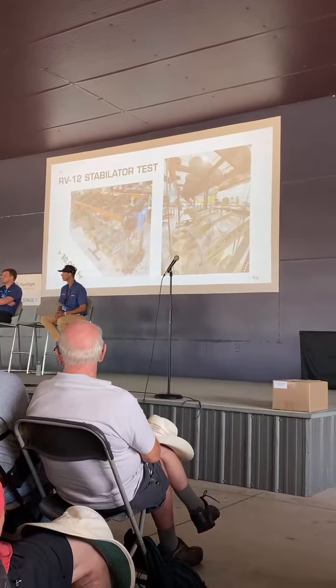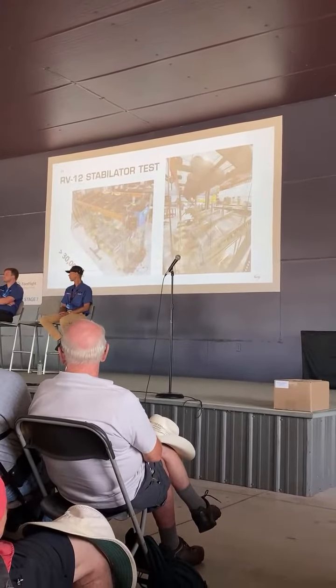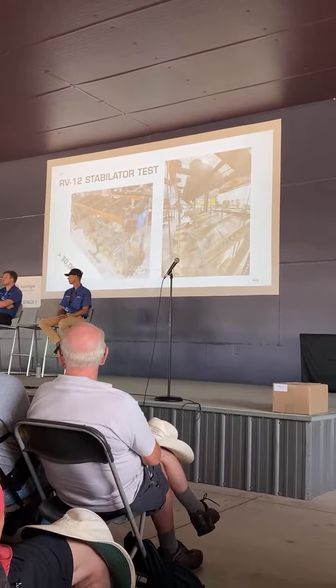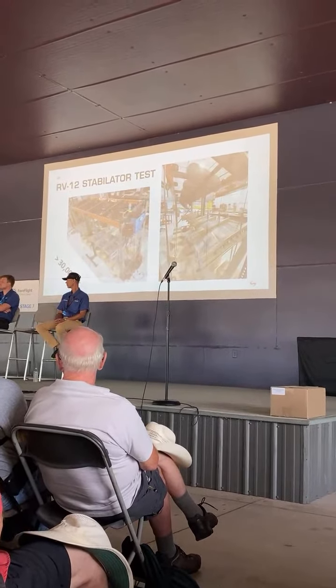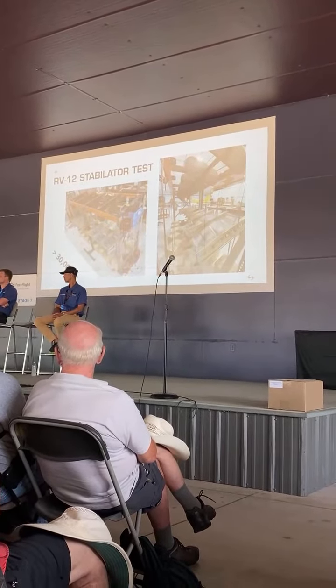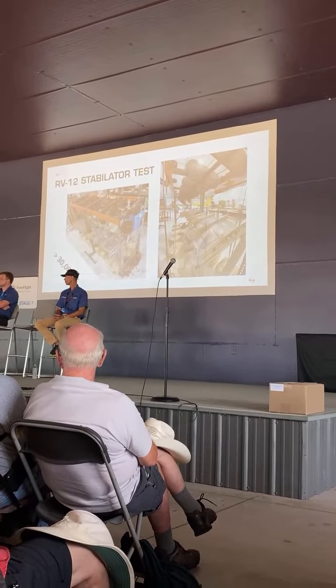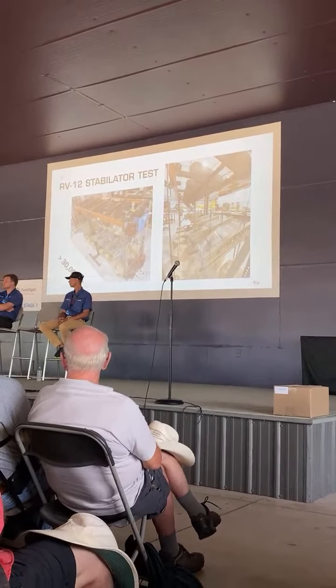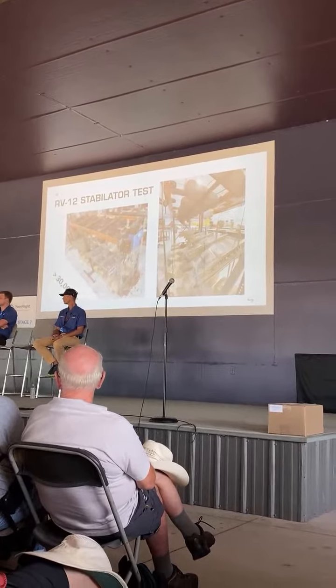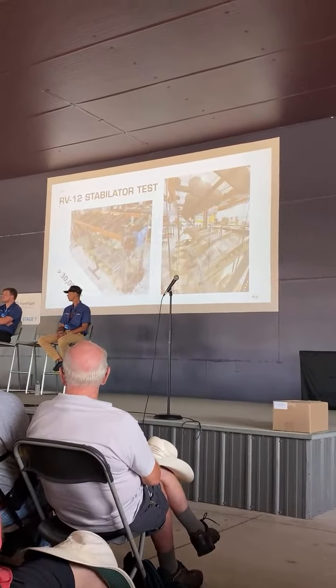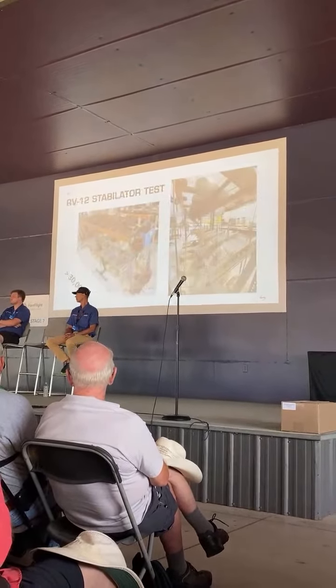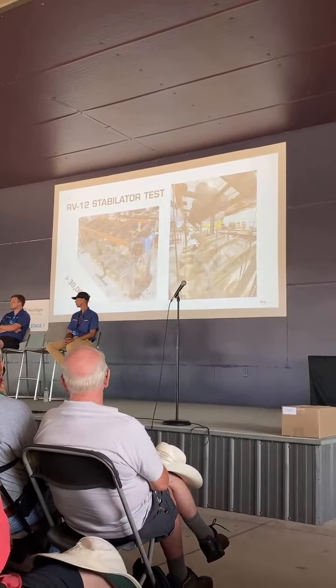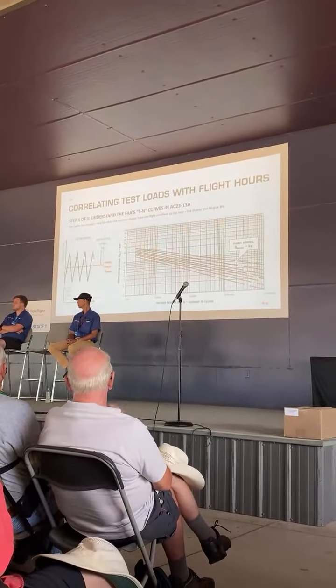And it's also highly loaded, as far as stress levels go: the amount of load at an individual rivet is one of the more highly loaded structures in an RV-12. So we went to over 32,000 cycles without any apparent effect on the structure. And we'll do further testing on that, failing members inside of it as well.